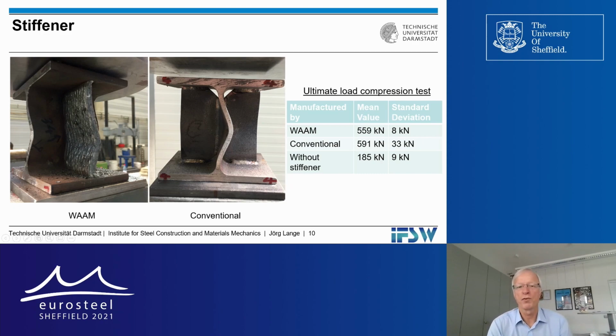We did the same with the same thicknesses of the plates with wire and arc additive manufacturing. We had a little lower mean value, but that always depends on the thickness you program. Here we had a little smaller thickness of the WAAM compared to the stiffener. Interesting is the small standard deviation in 3 tests. We had only a deviation of 8 kilonewtons, so much smaller than with a conventional one. And if you see the ultimate load without a stiffener, it's 185 with a standard deviation of 9 kilonewtons. So the WAAM product seems to be promising.